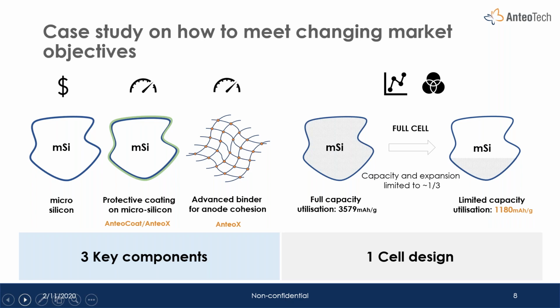Now, this microsilicon still needs to be modified and improved to ensure that the silicon cycles stably over hundreds of cycles. And the first step here is the application of protective coatings on the silicon, but also the binder plays a very critical role in facilitating anode cohesion and keeping all the materials together during repeated charge and discharge cycling. So these two components are absolutely critical to stabilize the performance of microsilicon. So out of these three main components, AnteoTech is very well positioned to potentially deliver on two, which is quite a good spot to be in for us.